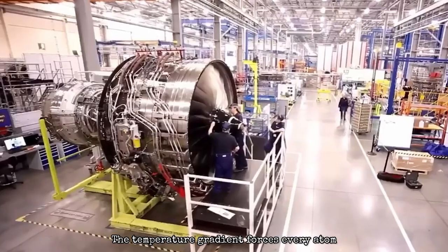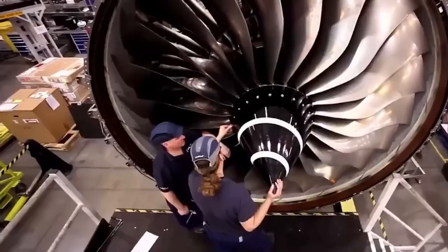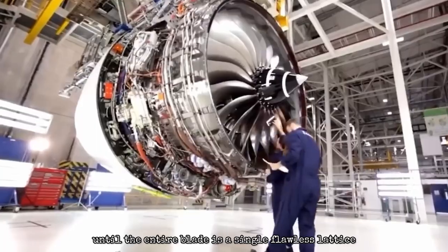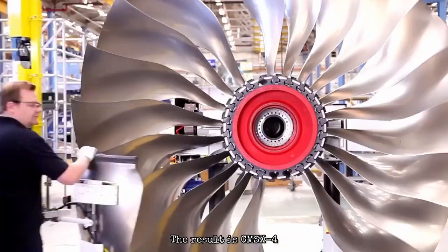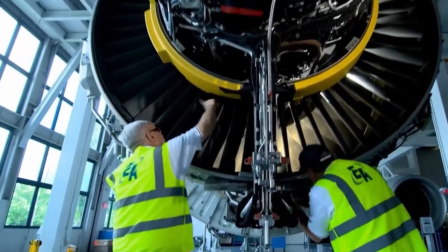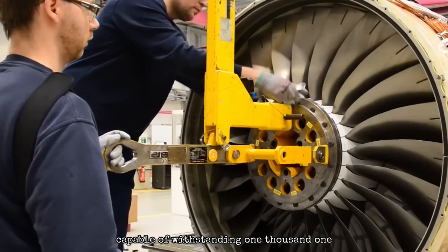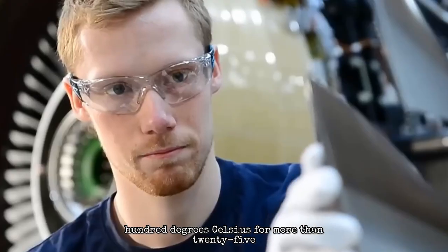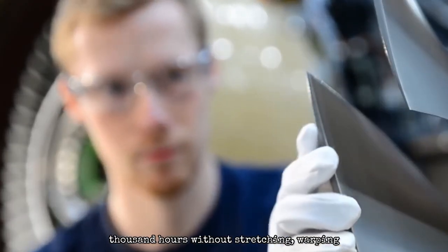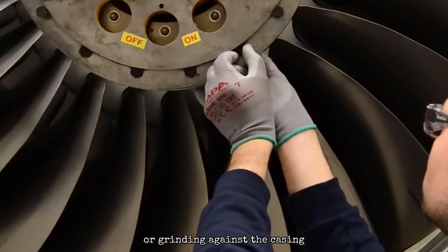The temperature gradient forces every atom to align, row after row, until the entire blade is a single, flawless lattice. The result is CMSX-4, the workhorse of US fighter engines, capable of withstanding 1,100 degrees Celsius for more than 25,000 hours without stretching, warping, or grinding against the casing.